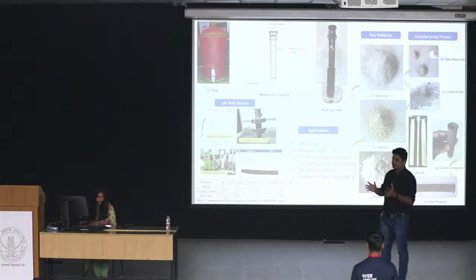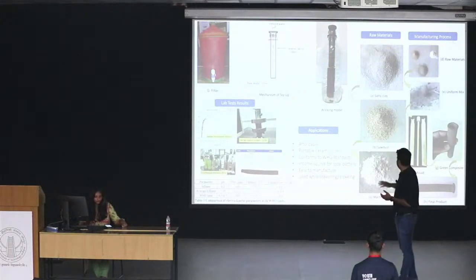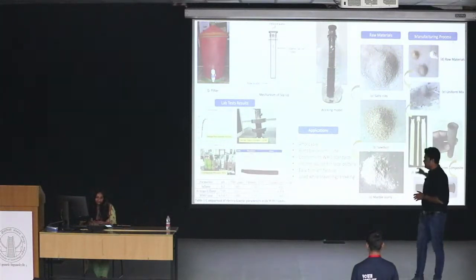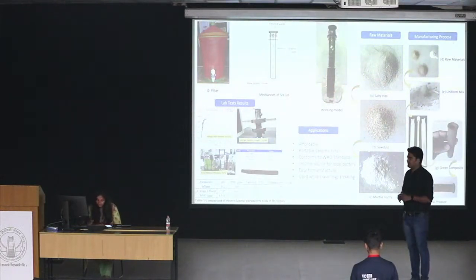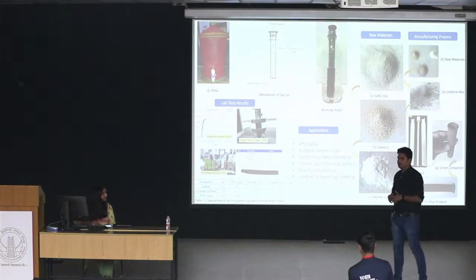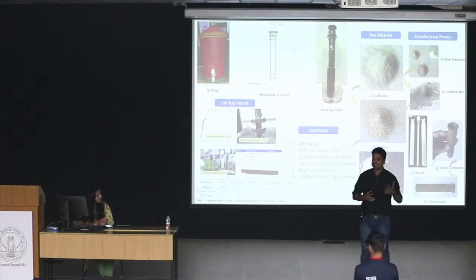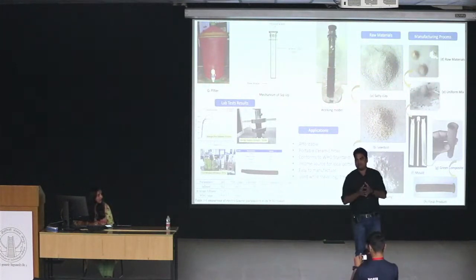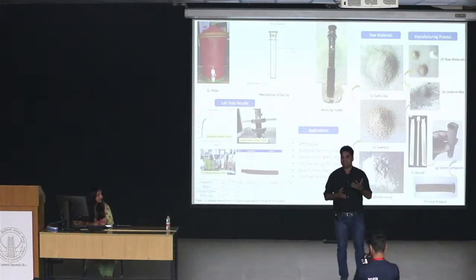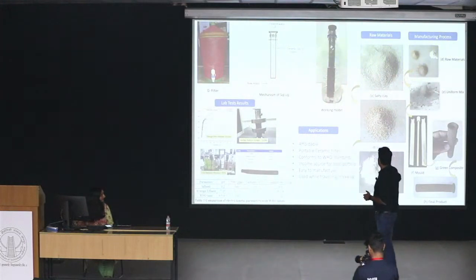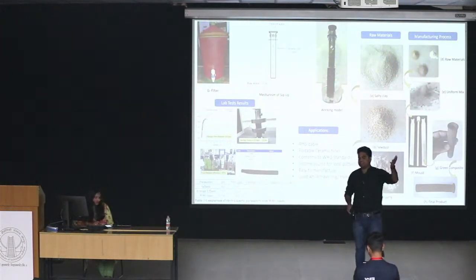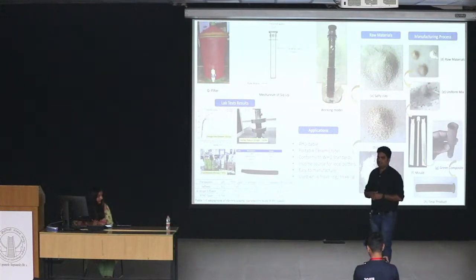So we have mixed all of them in a definite proportion. We have prepared a green mold, using a mold that we have prepared to make a uniform dimension all the way, and after that it has been kept in the open atmosphere for 2 days for drying, and then baked at 850 degrees Celsius in the muffle furnace. The product weighs around 68 grams and has a porosity of 43%.